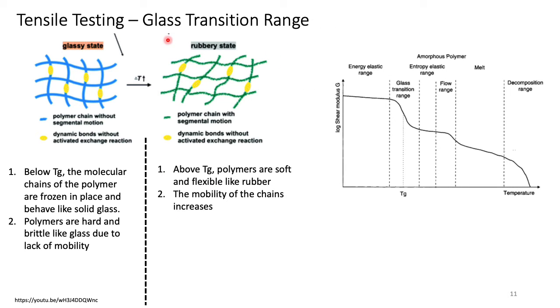So what's going on in the glass transition range, before the glass transition temperature and also after it? Before the glass transition temperature, we are at the glassy state. That means the molecular chains of the polymer are frozen in place and behave like solid glass. Polymers are hard and brittle like glass due to the lack of mobility. And after the glass transition temperature here, we are at the rubbery state, and above that Tg, polymers are soft and flexible like rubber, and the mobility of the chains increases.